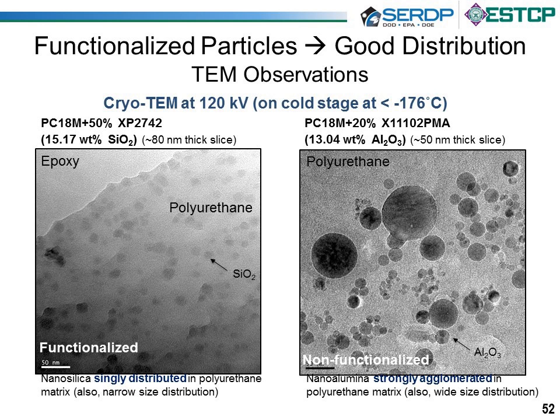And taking a look at the role of functionalization, we tried two particles, a silica-based nanoparticle and an alumina-based nanoparticle. In the silica base, we had some nice distribution of particles through the film. We can see here that these particles are very nicely distributed, and they're generally pretty uniform in size. In the nano alumina, we see some big particles and some little particles, and then there are these little submicron clusters that tend to form with this particular material. We found out a little bit later, and we'll look at that more on the next slide, that they were non-functionalized.